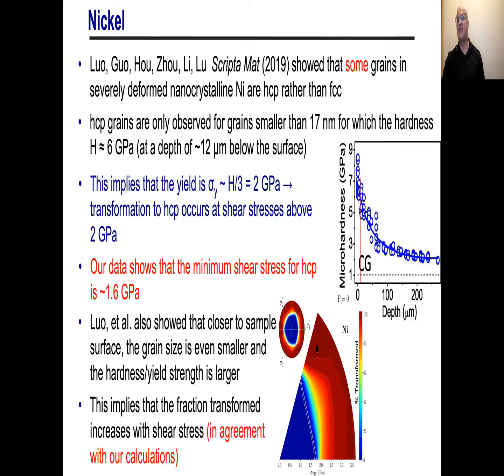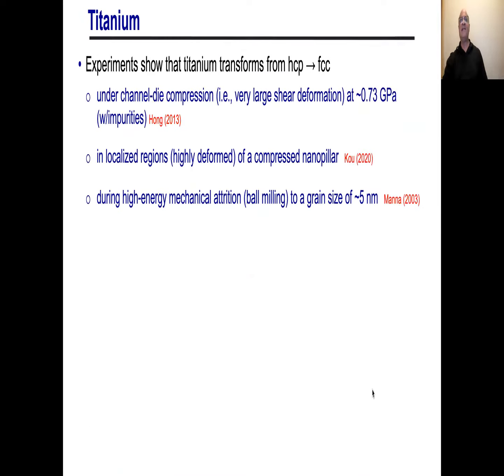So at shear stress about three, it would say that right at the surface, it should be possible to get something of order 70% transformed. Okay, and they also found they get more HCP grains closer and closer to the surface. So the one value we can actually make a direct comparison with is pretty reasonable, and the trend is also pretty reasonable. Titanium, well, it turns out I don't really have much good data on titanium that I can find